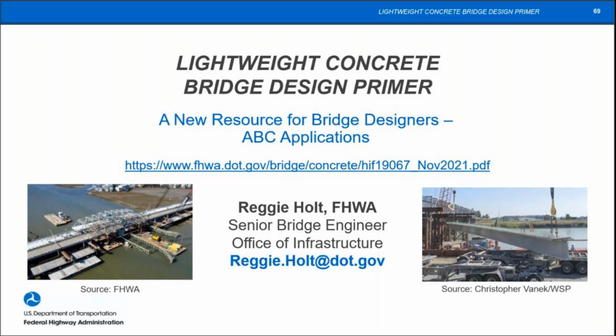Yeah, so the aggregates that I discussed earlier have been manufactured. There are some other aggregates that may be available in certain spots in the U.S., but the ones I am talking about are rotary kiln expanded shales, clays or slates. And that's basically what the U.S. specifications are addressed to. For example, in Europe, their aggregates do not perform quite as well as ours do. They have mostly expanded clays that are pelletized, and they seem to have reduced properties in some ways compared to ours. But ours are fairly uniform in the ways that they behave from the different sources. Some have capability of getting a little bit higher strength than others, but not all. So I'm not sure if that answers the question very well, but I think that's probably good for now, hopefully.